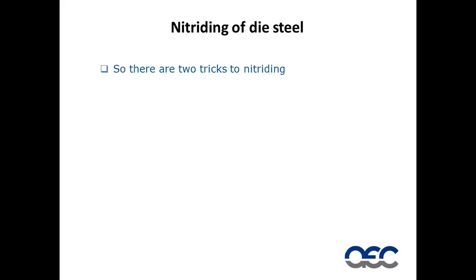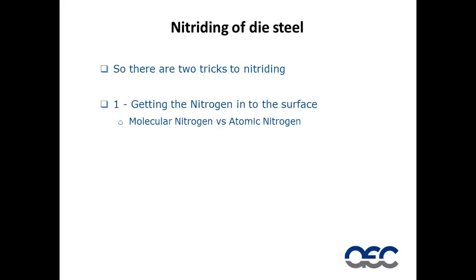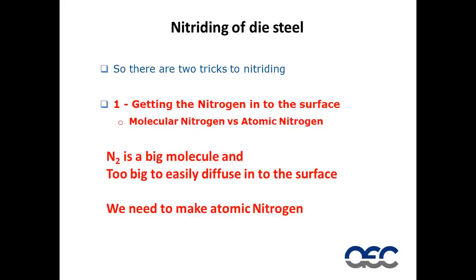So, there are two tricks to getting nitriding right. The first trick is to get nitrogen into the surface, because we have to get the nitrogen to penetrate into the die to a depth of around about 6 to 8 thou. Now, molecular nitrogen, which is what's in our air, is a big molecule. It's 2 nitrogen atoms together, just like oxygen is O2, nitrogen is N2. So as we breathe, sitting listening to this presentation, I hope everyone is, our lungs take in about 80% nitrogen. It's a sizable molecule, and it's too big to easily diffuse into the surface of a piece of steel. We need to find a chemical way of breaking this nitrogen molecule down into nitrogen atoms, which are then much smaller and can much more easily diffuse into the steel.